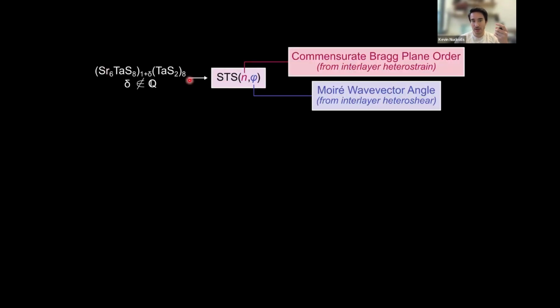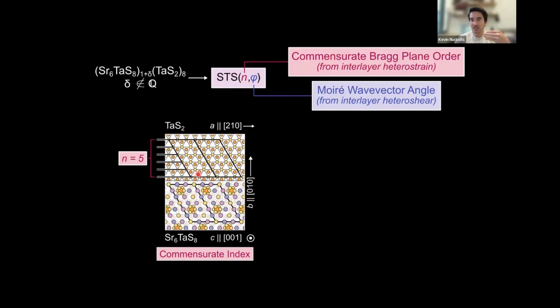So it's strontium, tantalum, sulfur, so we'll call it STS. And then we'll use two indices, one that captures the commensurate aspects of the interlayer coupling, and one that captures the incommensurate aspects of the in-plane lattice. So this commensurate index n is an integer, and effectively it just tells me how many of the Bragg planes are shared between these two lattices. So you can see very specifically in this compound, the top and bottom of this unit cell in the spacer takes 1, 2, 3, 4, 5 unit cells in the tantalum disulfide, so n equals 5.